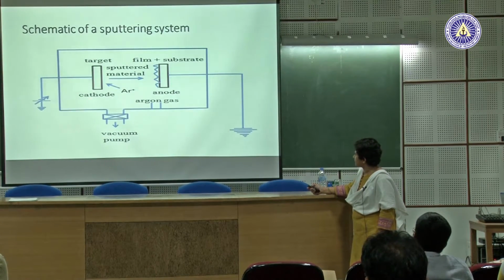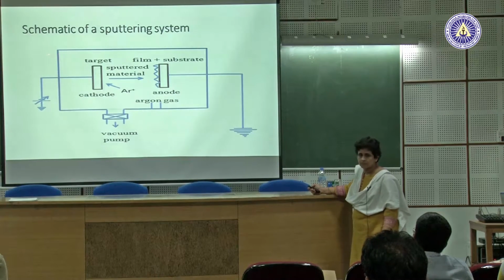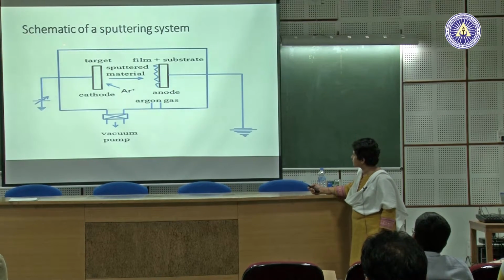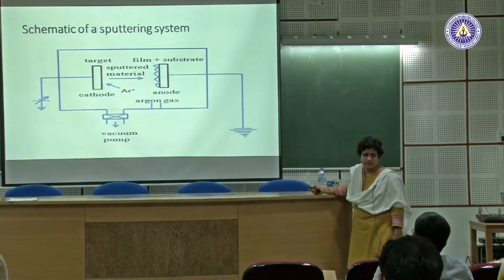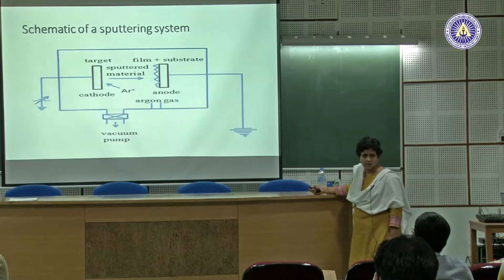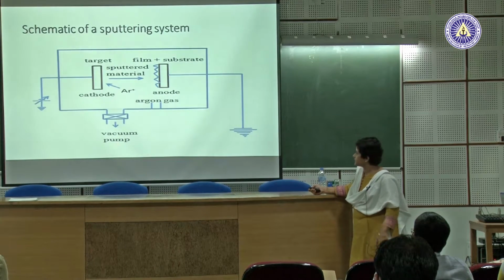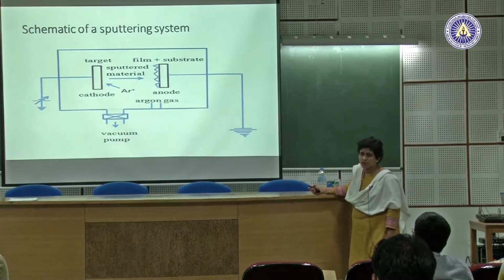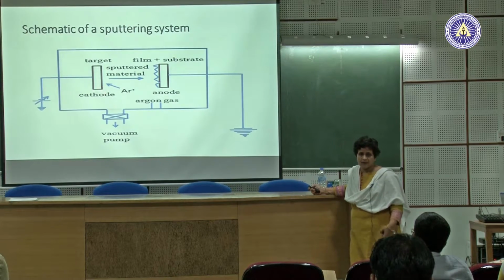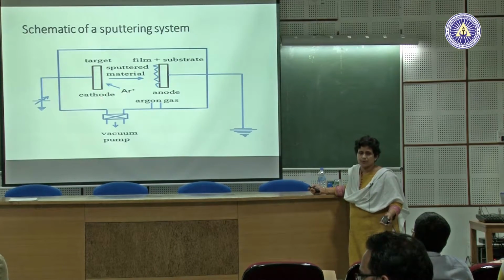In the schematic part, basically the sputtering of a thin film chamber, this is only the picture of the chamber. Again, this has to be done in vacuum for the similar reasons that we did for evaporation. You do not want contamination at very high energy atoms. There is a cathode surface, and then there is an anode surface. The cathode surface is normally what you want to deposit. It is the target material. I want to deposit aluminum, it will be aluminum. I want to deposit copper, it will be copper.